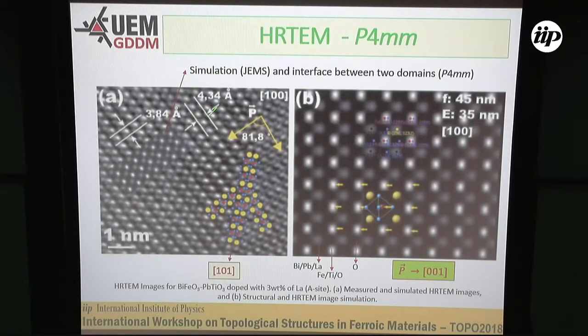When you calculate the tetragonality factor, you see that it's about 12%. This is the same number that we have using X-ray and neutron diffraction in the Rietveld refinement. And we see that the zone axis is 100, and the polarization is in 001, because you have these atomic positions from our simulation. We have the atomic positions here. And we see here a very, very thin interface separating two domains.